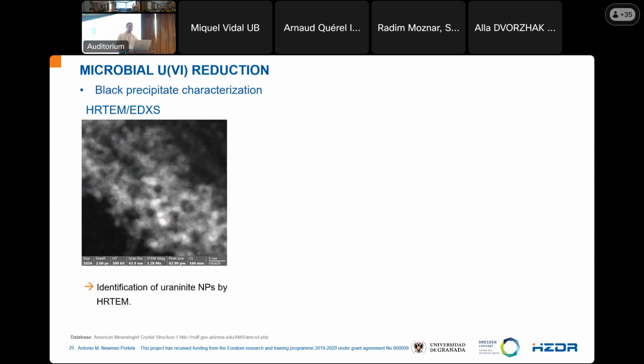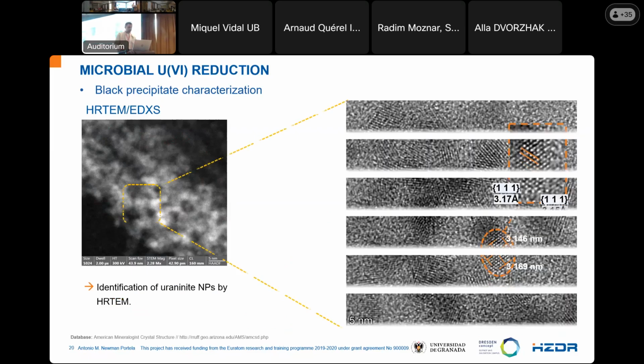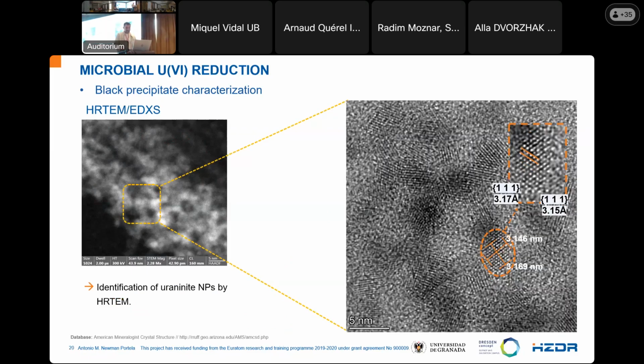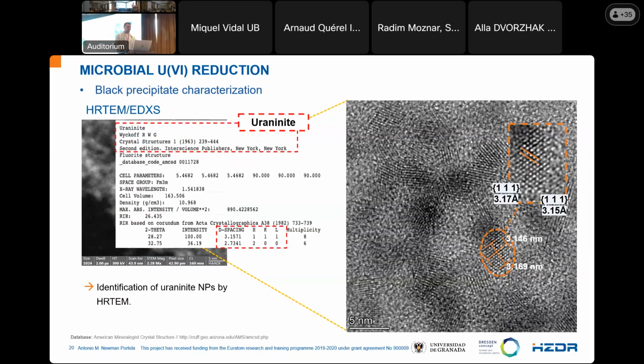Thanks to the high-resolution transmission electron microscopy, when we analyzed the accumulation, we were able to identify these nanoparticles, measure their lattice spacing, and compare this lattice spacing with the database. We confirm that these nanoparticles are uraninite nanoparticles.